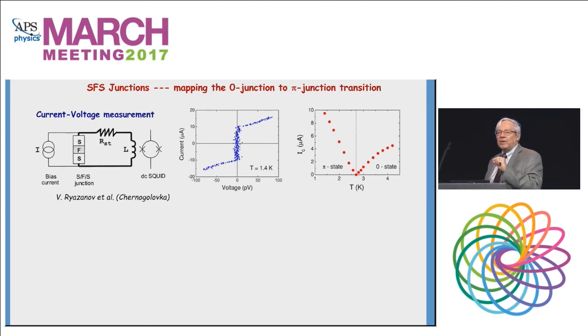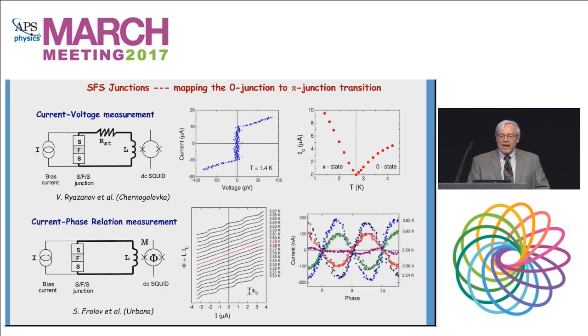But you can't tell whether there's a phase change or not. To do that, you have to use a current phase relation technique. So here are experiments where we, again, took a junction, embedded it in a ring, and here's the modulation patterns. You can see there's a modulation. It goes to 0 at a particular temperature, then it comes back, but notice the wiggles are out of phase by pi in this junction.